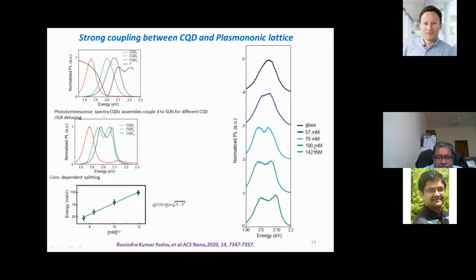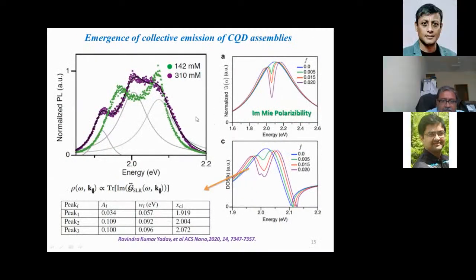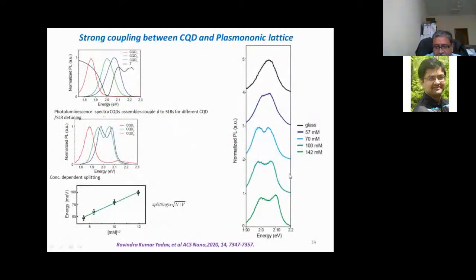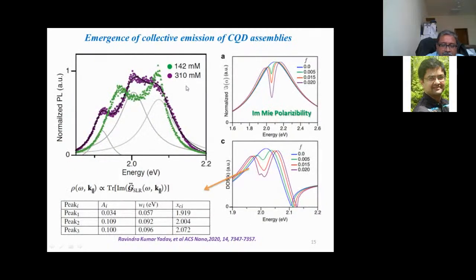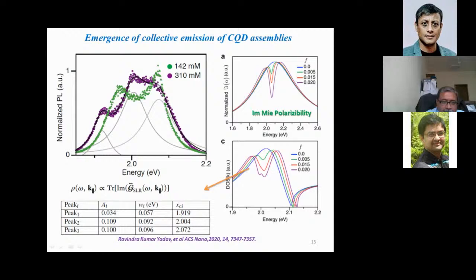So we push this limit further, and this is now comparative data between what I showed here, which was the highest concentration, and when we pushed it, almost doubled it. When you do that, you see very clearly that something is emerging here, a third peak or mode. This is very, very clear. So now the question is, what is this? What is basically causing this one?